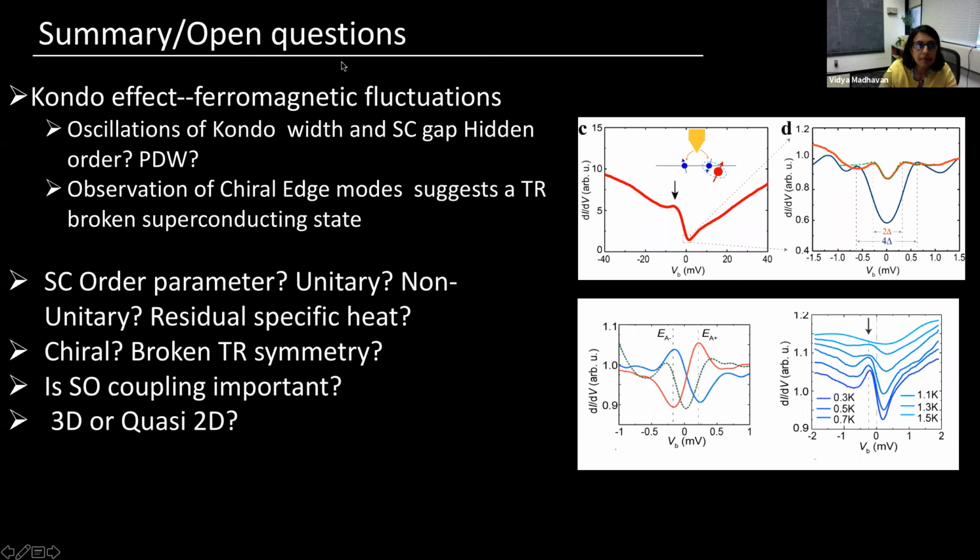Another question from Younglang. Hi, I have a question regarding the superconducting gap. Do you see any response, for example, in-gap states near atomic impurities, either magnetic or non-magnetic? No. All our in-gap states have been at step edges. We've seen in-gap states on all the step edges that we've looked at, but nothing dramatic. Again, we have the shallow gap, so I don't know what's hiding underneath it, but nothing dramatic at impurities.